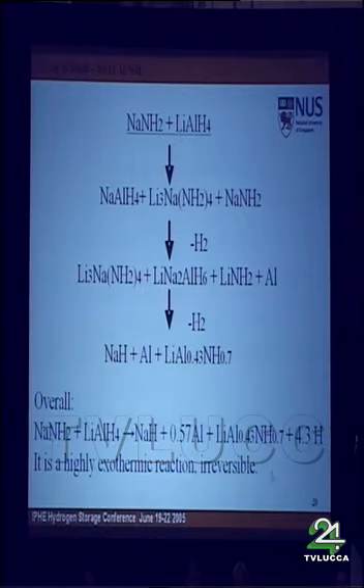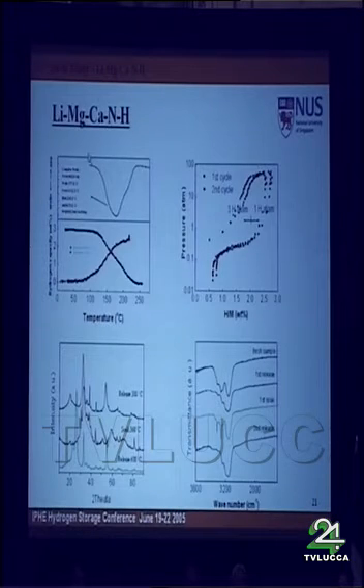So overall, we get such a chemical reaction which gives us more than 5% hydrogen release at room temperature. However, it is an exothermic reaction and is hard to make reversible. And this is our another attempt to work on multinary nitrogen hydrogen systems. In this case, we use lithium, magnesium, calcium, and investigate the hydrogen absorption and thermodynamic performance of the system.